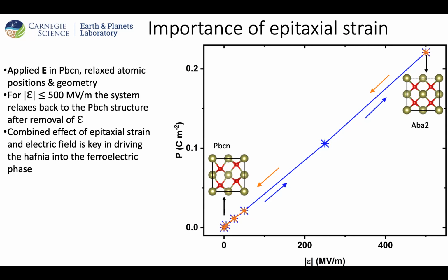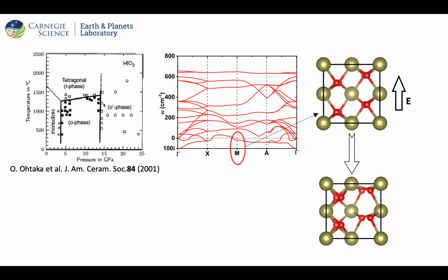Now I come to the story, I guess, of why we start with the PBCN. Professor Karin Rabe actually brought a very good point earlier in her presentation of the polar zone-boundary soft mode driven phase transition in hafnia. Here, when you start, let's say, with a tetragonal phase from, let's say, 2000 degrees Celsius, and then apply epitaxial strain. So when you expand, for instance, the tetragonal, you will see all these soft modes pop up all across the Brillouin zone. The soft mode at the M point will lead you to that PBCN phase.